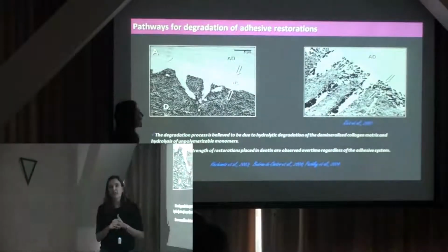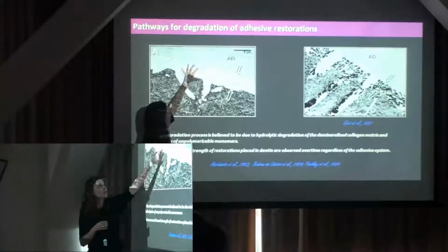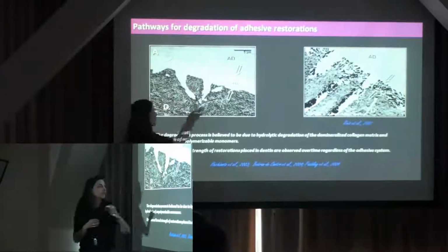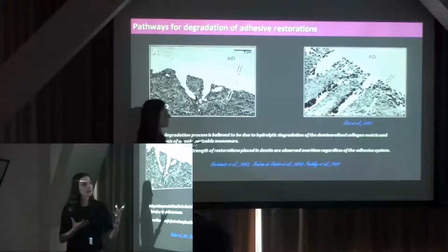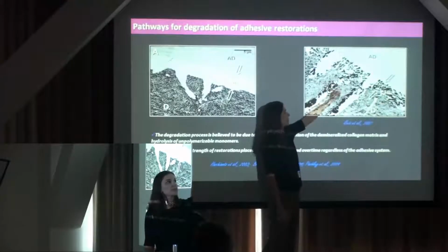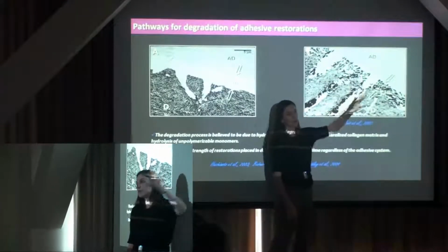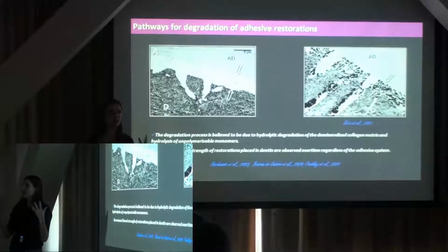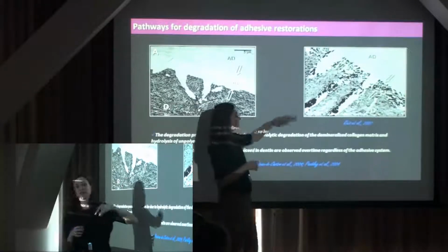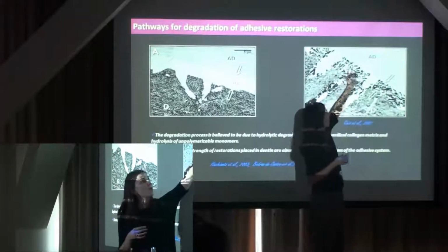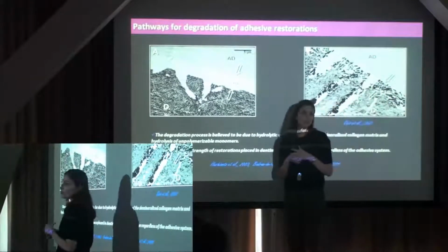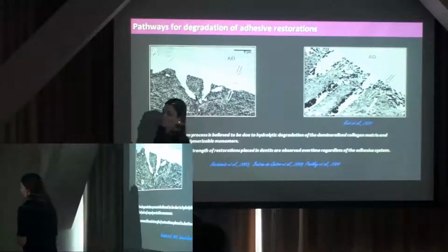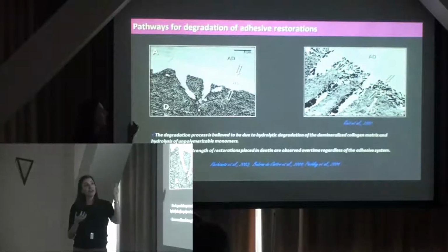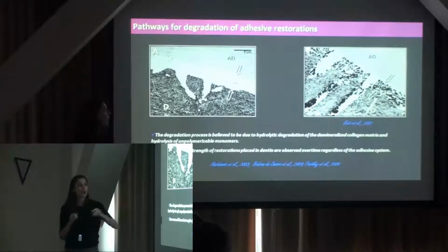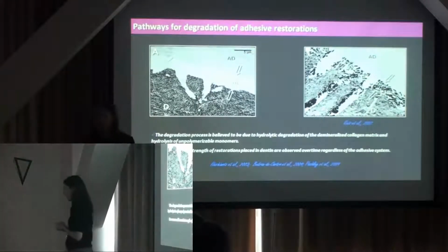When I showed you that hybrid layer, this is a transmission electron microscopy image of it. We have the collagen and the monomers, and over here the adhesive. This is a basic study that we do when we want to look at the permeability of this interface. All these black particles are showing us porosities, and these are silver nitrate particles. We infiltrate with silver nitrate over a 24-hour period, section these small, and see where our defects are. What we know is that over time, the porosities take place exactly at this hybrid layer. So while we need the hybrid layer to be formed during the restorative procedure, it is our weakest link as well. Every process of defect initiates there.